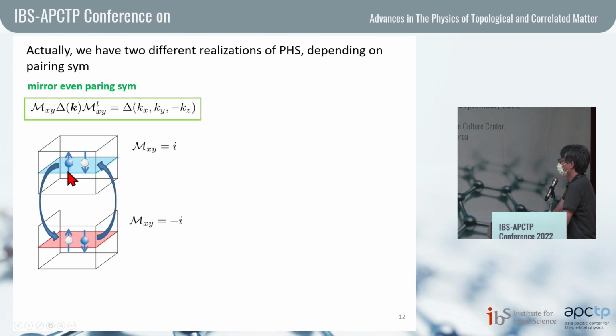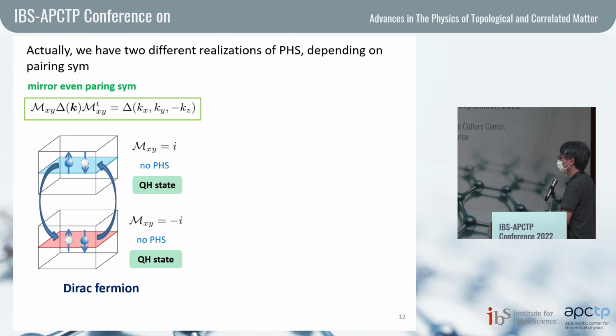Actually, if you apply the particle-hole symmetry to the up-spin electrons, we have an up-spin hole in the different mirror subsectors. We also found that if you apply the particle-hole symmetry to the down-spin electron, we have a down-spin hole in the different mirror subsectors. So for the whole system we have a particle-hole symmetry, but each mirror subsector doesn't have a particle-hole symmetry. This means that each mirror subsector realizes a quantum Hall state like ordinary topological crystalline insulators. So, like ordinary topological insulators, we just obtain the Dirac fermion in the system.